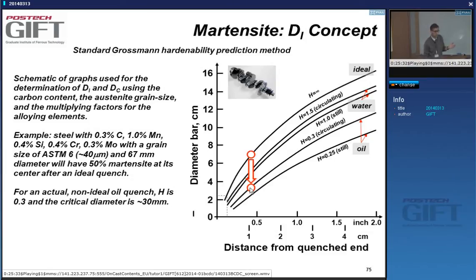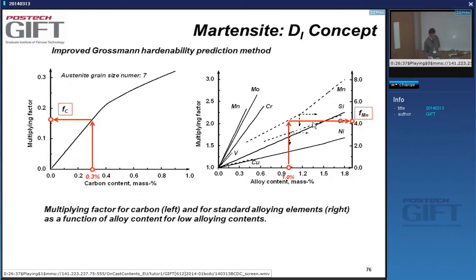So that means that engineering steels, when they are produced, the composition that is required from the manufacturer may include requirements related to DI value, which is composition dependent. For what kind of products does this happen? It doesn't happen for sheet products, because heat treating sheet products is very easy. They're only millimeters thick, right? But for bar products, things you make crankshafts with, for instance, it's important to have a composition that gives you the right DI value. So you're sure that the material you made has the correct amount of martensite in the microstructure after heat treatments.